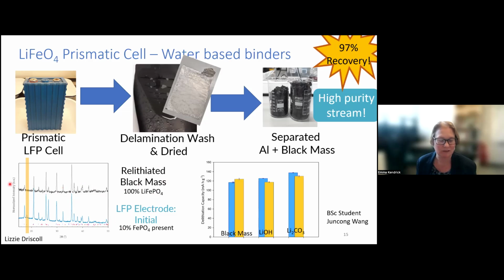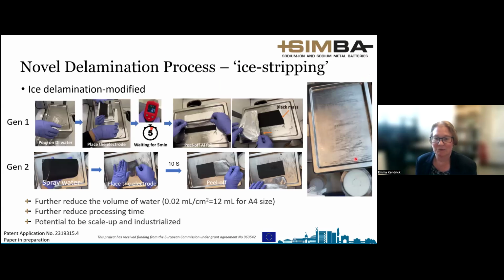And then relithiating it, we can recover and remanufacture the lithium iron phosphate. We get some capacity back, but the quantity of carbon that we end up with in this system is actually quite high, and we need to look to try and improve or reduce the level of residual carbon from this carbothermal process that we've used to remanufacture the lithium iron phosphate. But it's a good start, and it shows that water-based binders are an efficient way of removing some of the issues associated with PVDF binders that only dissolve in things like N-methylpyrrolidone or NMP. In this process, we got 90%, 97% recovery of our lithium iron phosphate from the cell, which is quite a good achievement. But we're still trying to reduce some of the waste that we produce from these processes.